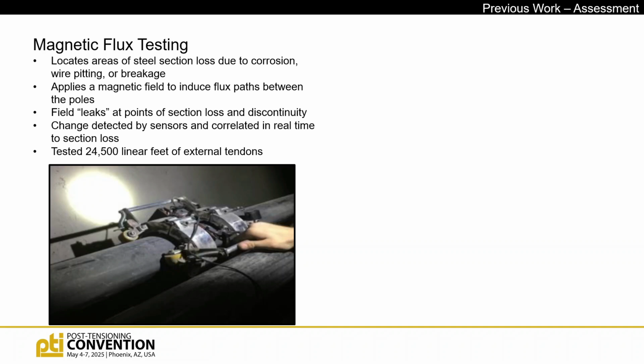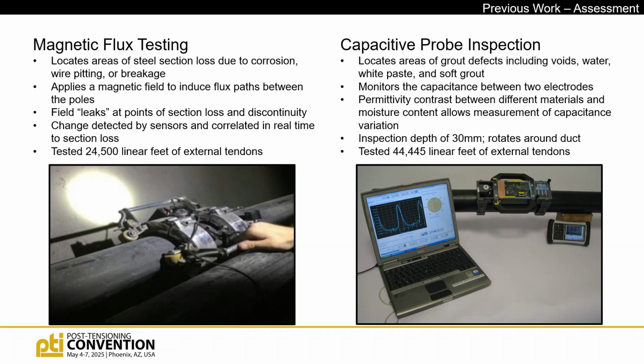The other piece of this was magnetic flux testing. What this really is, is magnets that are on a steel frame, a rolling steel frame that can run along the free length of the tendon. Those magnets induce a magnetic field that leaks at points of discontinuity in the strand where you have wire breaks or corrosion. And then you can measure that in real time and correlate it to an amount of section loss. And it's a similar looking little device.